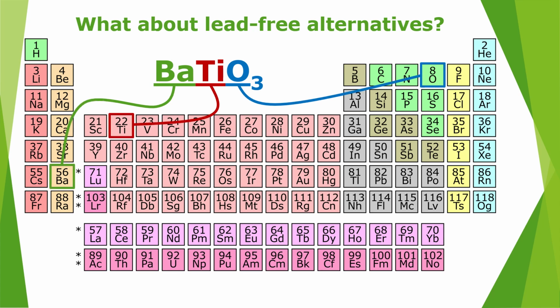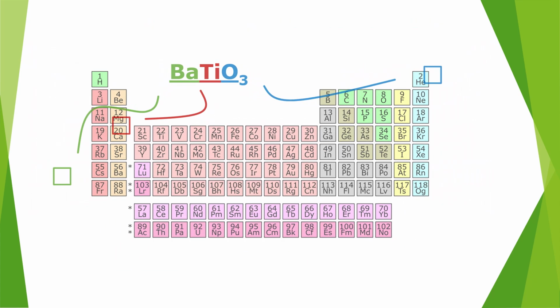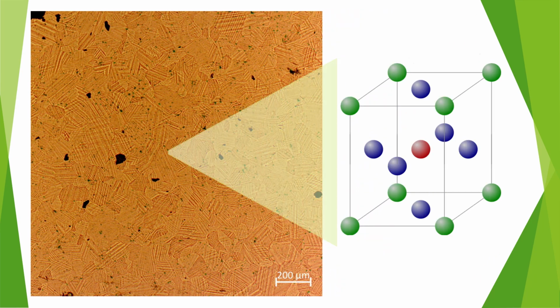Barium titanate-based relaxors count among the most promising lead-free candidates, and this is what the material looks like in an optical microscope. We see that the material is comprised of grains, and the grains are organized in so-called ferroelectric domains, forming a striped pattern. Zooming further in, we can see the smallest building block of such a domain, a unit cell of a perovskite crystal. The colored spheres represent the individual barium, titanium, and oxygen atoms. What makes ferroelectrics like barium titanate so unique is that the titanium atom displaces from its central position, creating a permanent dipole that can be even switched if an external electric field is applied.